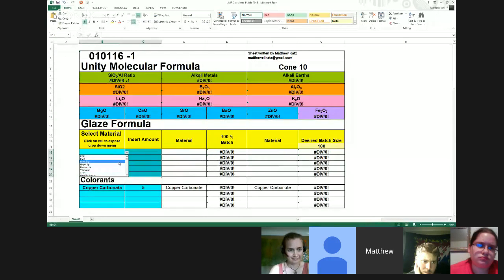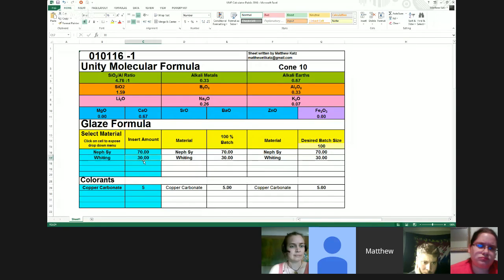We could look at that at the most simple level. Let me open the glaze calculator. I shouldn't have stopped sharing. If we come in here and just do Neph Sy and whiting, and we balance these for the most part, 33, 34. With Neph Sy and whiting, this is the lowest amount of silica and alumina we can get in a stable glaze. Of course, we don't have any clay in this, but take note, our alumina level is at 0.3. So that's still pretty high for trying to get into that lower wollastonite region, that one tiny little corner back down here.